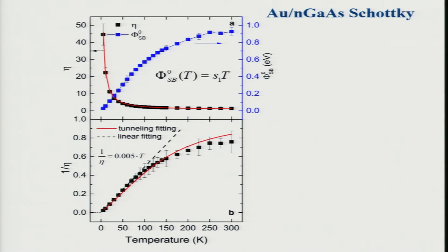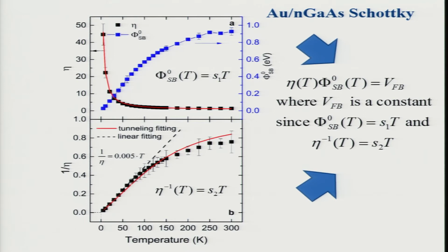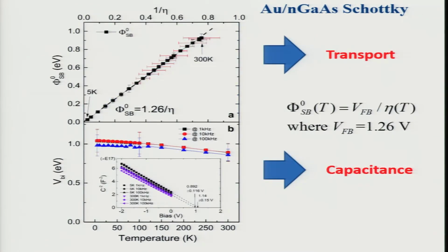So here's your coefficient describing the linear temperature dependence of the zero voltage Schottky barrier height. Here's the temperature dependence of the inverse of the ideality, another slope. The product of these two is independent of temperature and gives you the flat band voltage, which you can show from this. I'm not going to go through all the analysis, but you can show that using that probability distribution and going through all the averaging over a Gaussian distribution over this thermionic equation. So that's what we see for gallium arsenide Schottky barriers. Okay.